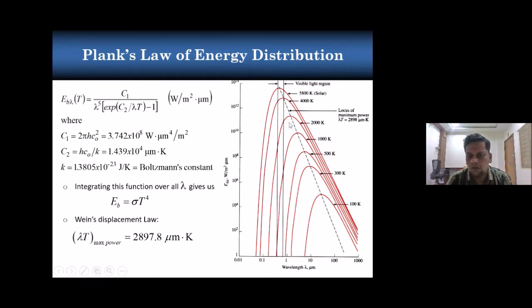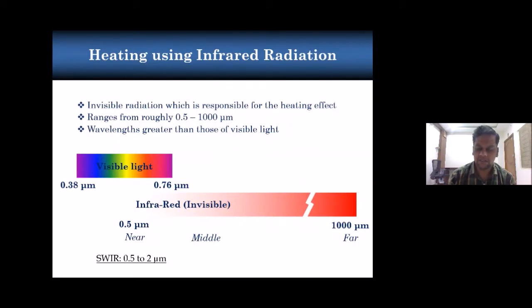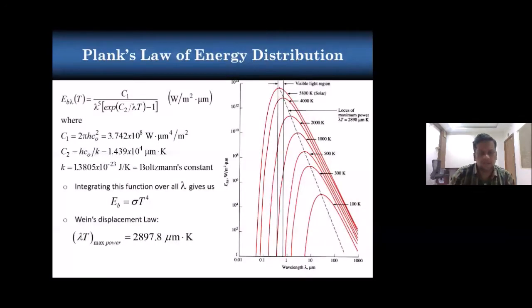Now if you see the locus of the maximum power, that gives you a relation called Wien's displacement law, which tells you the relation between temperature and wavelength. You can see here that maximum temperature is inversely proportional to wavelength. As the wavelength becomes small, we can achieve maximum temperatures at the source level. I'm talking about the source level. In our case, the source is the infrared lamp filament. That's why we are talking about short wave infrared lamps. In medium and far wavelengths, we may not achieve higher temperatures as compared to short wave.